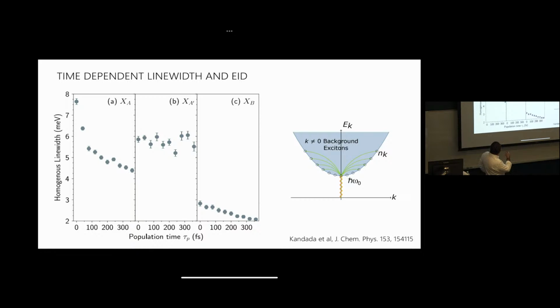So your initial gamma 0, at this particular density, for XA and XB is very different. So very different dephasing to begin with, because of this polaronic protection from exciton-exciton scattering. But as normally happens in these experiments, you excite, you generate some population, and then you have spectral diffusion, things diffuse. You start out from a narrow distribution of states that you create optically, and then these evolve to a broader distribution of states. You should get spectral